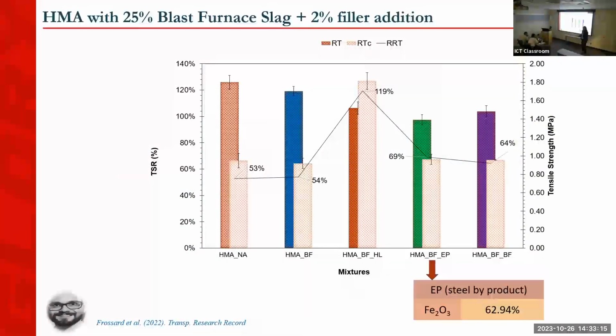But can I use blast furnace slag? It doesn't have good adhesion. Is there a way to improve it? One way is by adding additives, such as hydrated lime. Everybody knows that to minimize moisture damage, you can add hydrated lime. So we added 2% hydrated lime to the original mixture in which we replaced natural aggregates by 25% BF slag. When we added hydrated lime, the tensile strength ratio increased, which was the result we were expecting.